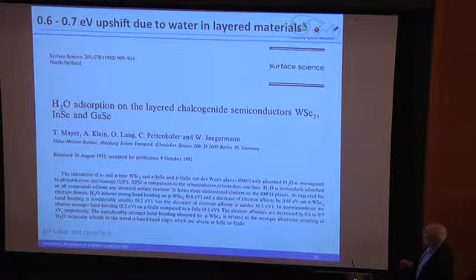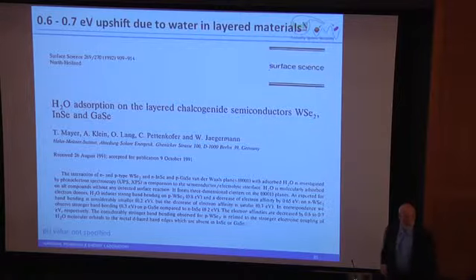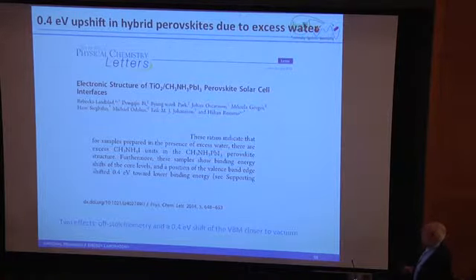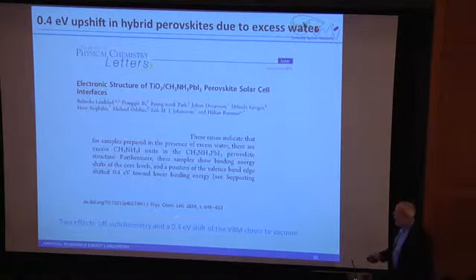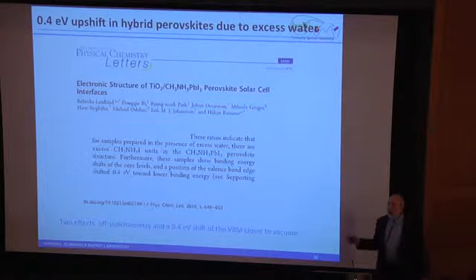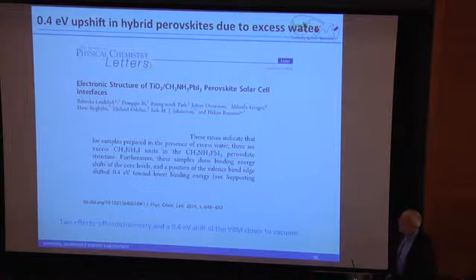However, if you look at H2O absorption on layered chalcogenides, I love this, the difference is from 0.2 to 0.7, and the average is 0.5. And in general, they see just about exactly what we're reporting. If you look at perovskites, I had to put it in, you see the same thing. You see about a 0.4 eV shift. So it appears to be pretty ubiquitous. So maybe we're just that insensitive. If we can get the PZC right, now what would be really great, hint, hint, is to be able to calculate the point of zero charge for a material, which has a lot to do with those different surface orientations and how essentially acidic or basic they are. So if we can do that, that would be great.